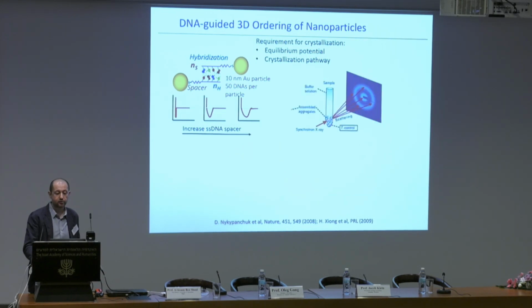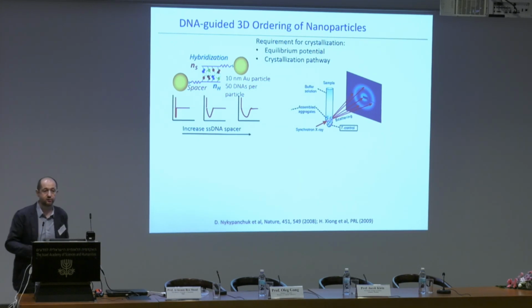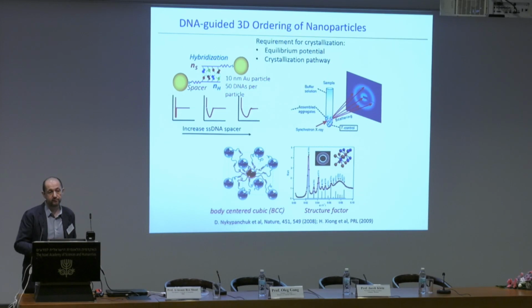It was important to realize that we need an in situ tool to trace and monitor the system transformation and how it goes to crystallization. From this point of view, we have been relying heavily on X-ray scattering, which can be done in solution, and by analyzing the two-dimensional pattern, we can extract information about structure. By optimizing this interaction potential as well as the pathway, we were, for the first time, able to demonstrate three-dimensional crystallization of nanoparticles driven by DNA. I just want to mention this, like 10 nanometer gold particles, 50, 60 DNA per particle. That gives you the ability to create these crystals.